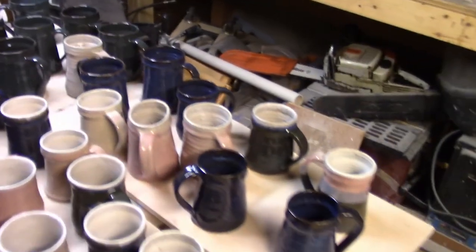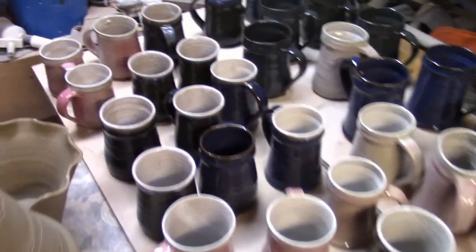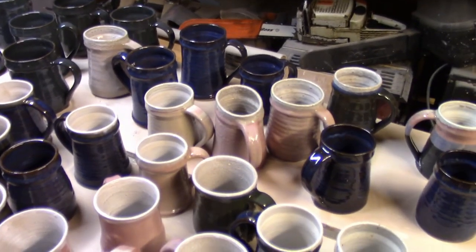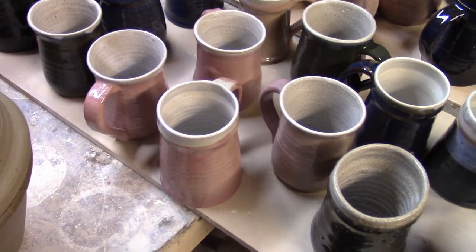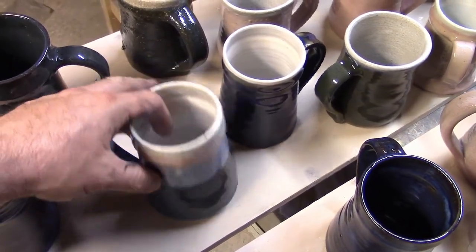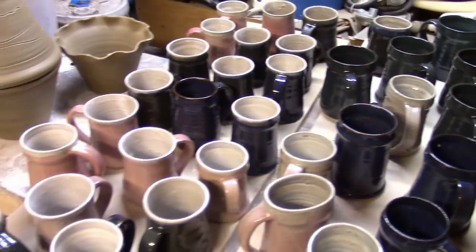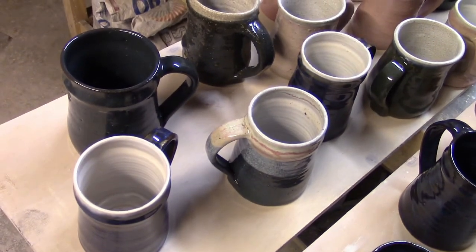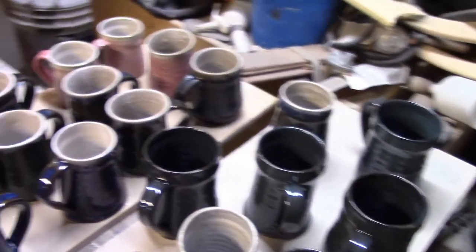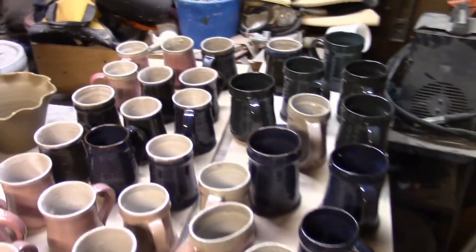All in all out of all these I probably have about 10 that I can maybe salvage - nothing I could ever sell, just throw them up in a cabinet. I took some good notes and hopefully next time will be better because that pink is really bad. I need to step up my glazing game - terrible, ugly. I'm not quite convinced that this glaze fits this body because once in a while I hear that tink tink sound that the glaze is unhappy with the body. Let these set a couple days - no crazing though, which is good, so it's close. More failures - you can't win them all. Thanks for watching.